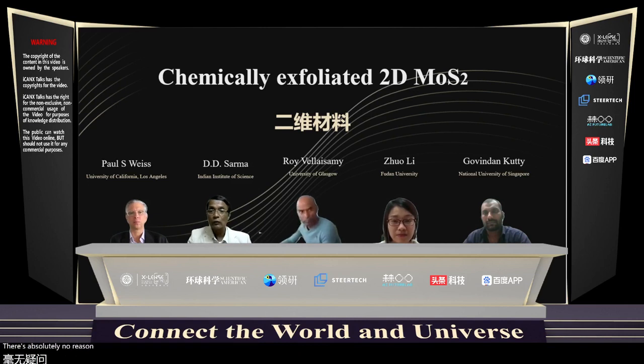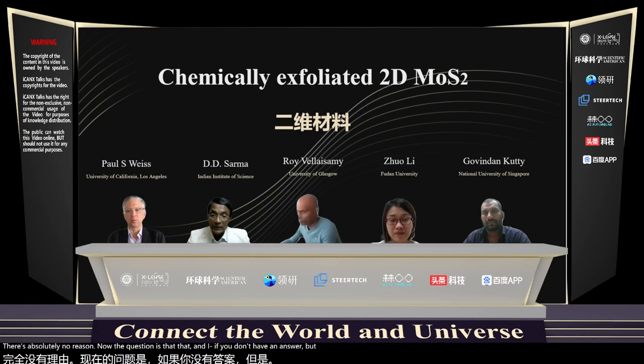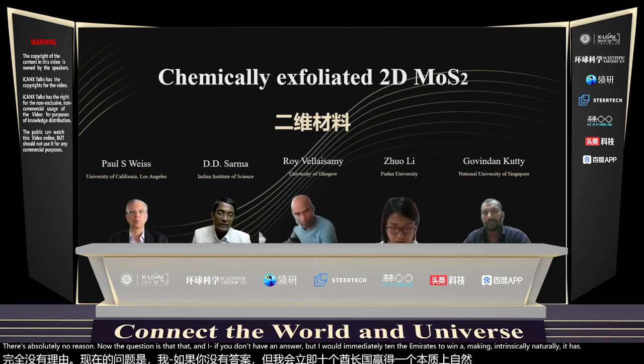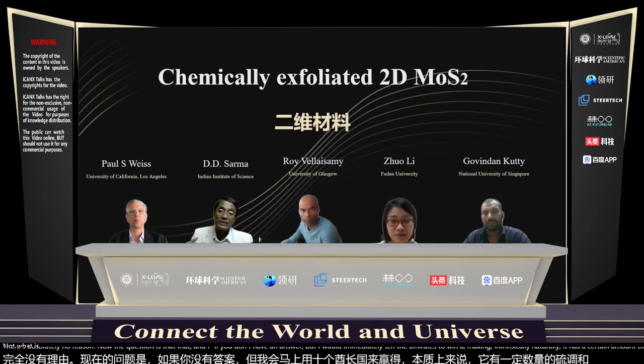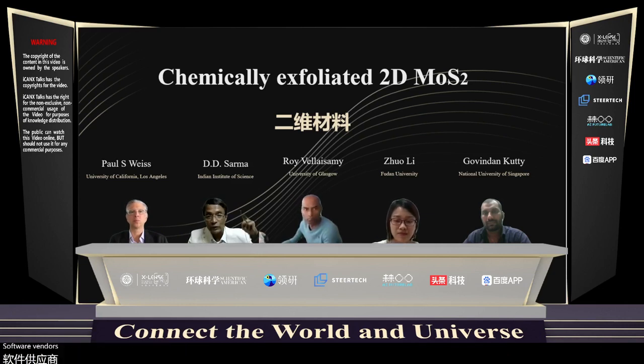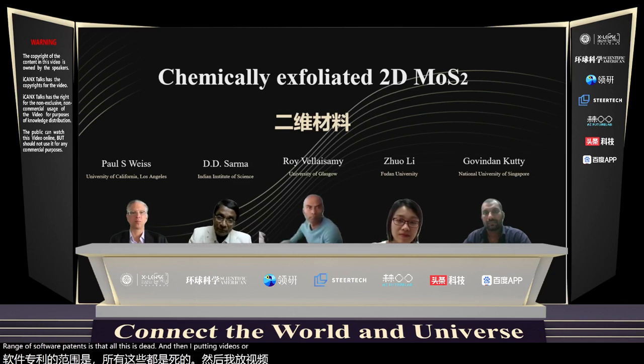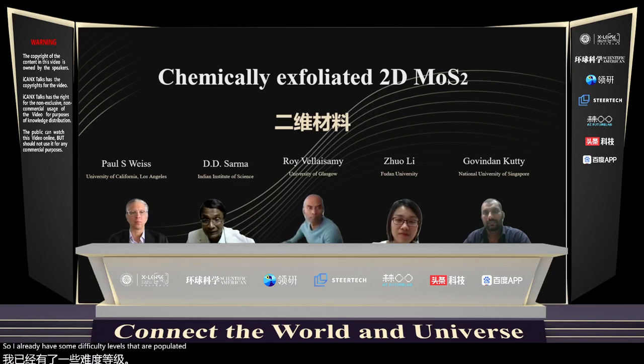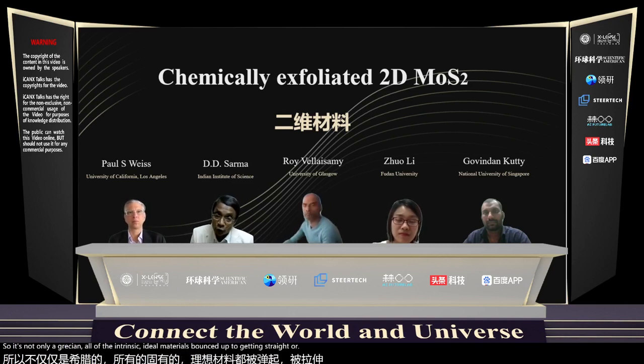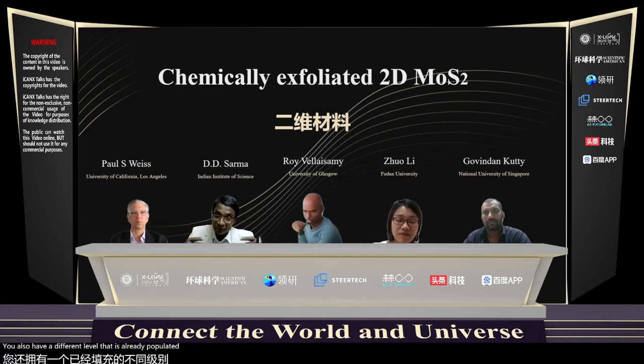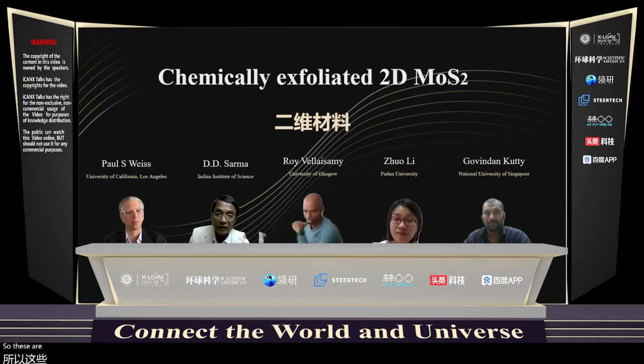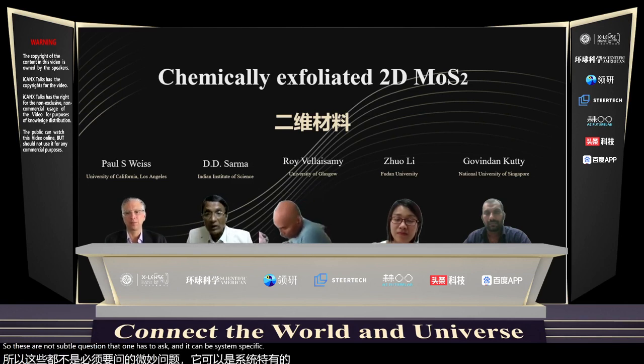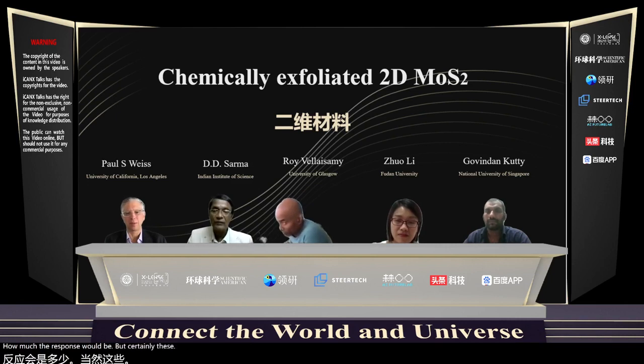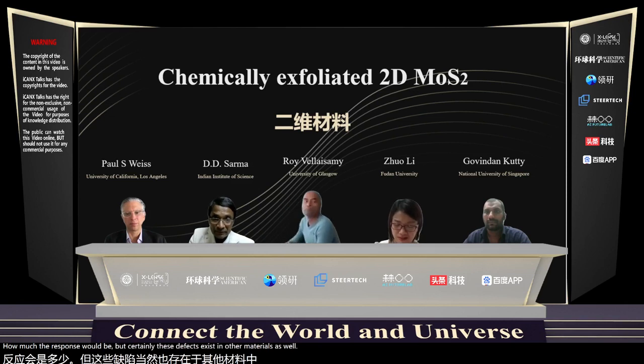There's absolutely no question. Now, the question is, and I again don't have an answer, but I would immediately think, see, MoS2, when I'm making it intrinsically, naturally, has a certain amount of sulfur vacancy. Now, what is the synergistic effect that I get? Having those sulfur vacancies doping 2 electrons each sulfur vacancy, there's a range of sulfur vacancies that always is there. And then I'm putting lithium or strain. So I already have some defect levels that are populated. So it's not only a question of the intrinsic ideal material's band structure getting strained or doped. You also have a defect level that is already populated. And how that responds, these are the subtle questions that one has to ask, and it will be system specific, how much the response would be. But certainly, these effects exist in other materials as well. Yeah, that answers my question.